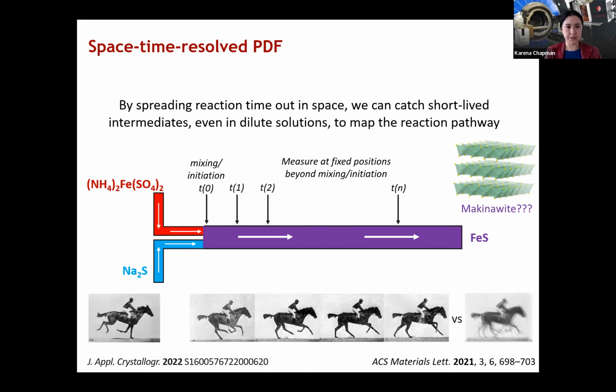The initial test case system we looked at to test out this approach was the formation of mackinawite, an iron sulfide, a layered iron sulfide structure with tetrahedral iron sulfurs that are edge sharing. People have described the formation of some kind of amorphous or nanoscale intermediate in the formation of mackinawite, but they weren't able to characterize it and capture it before it transformed to mackinawite.